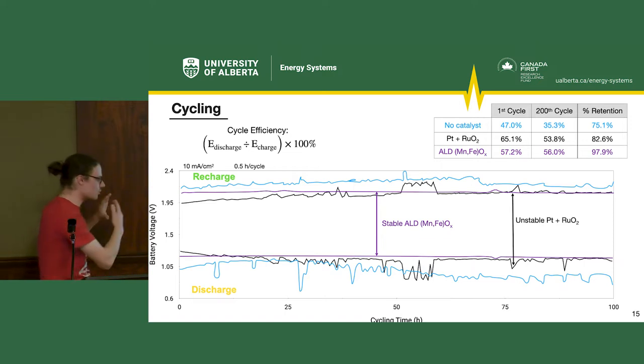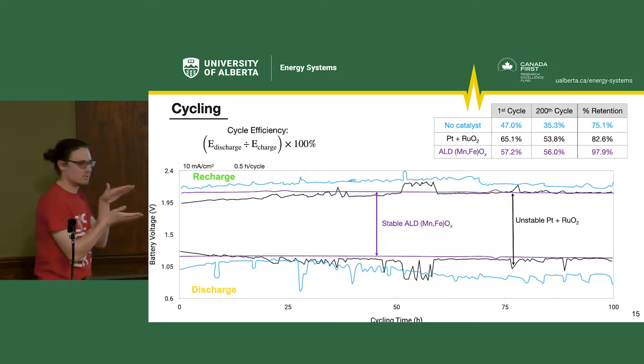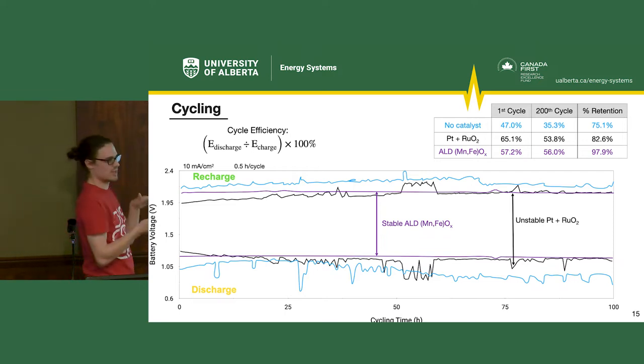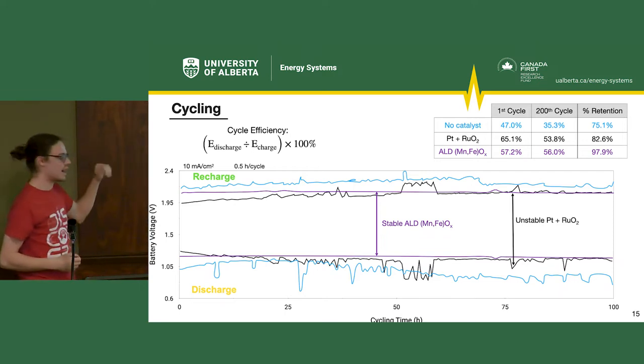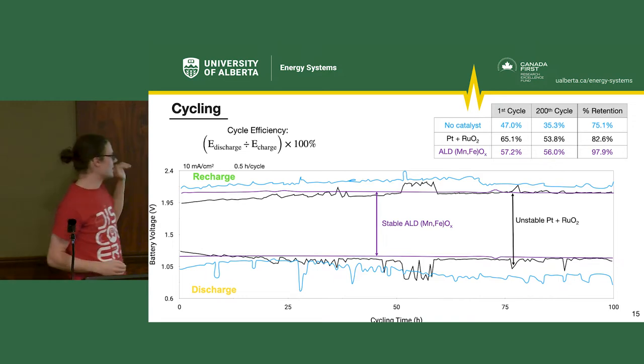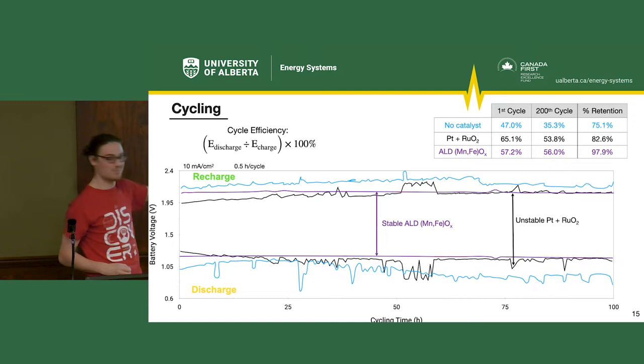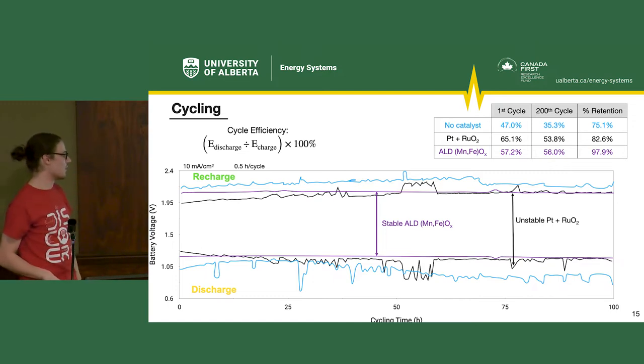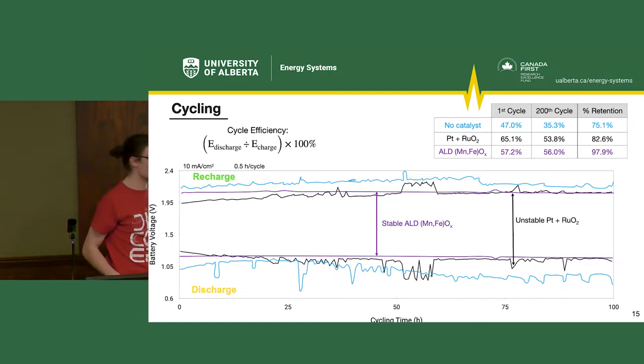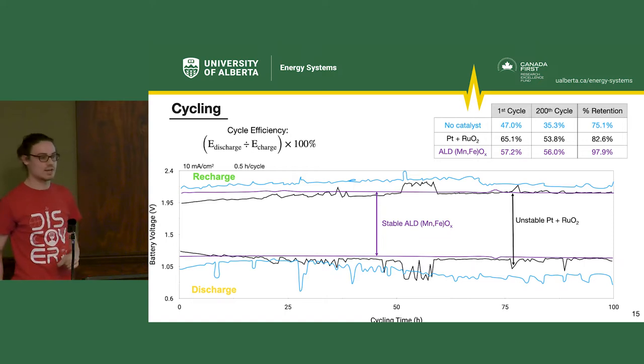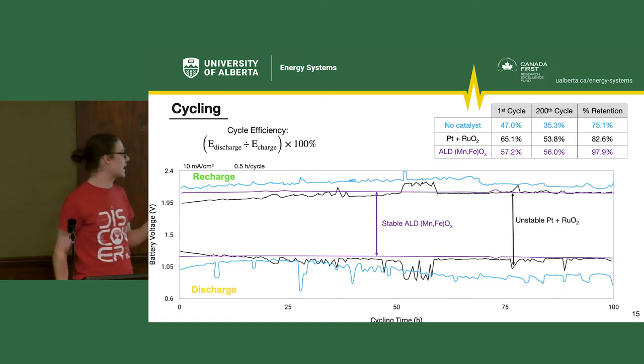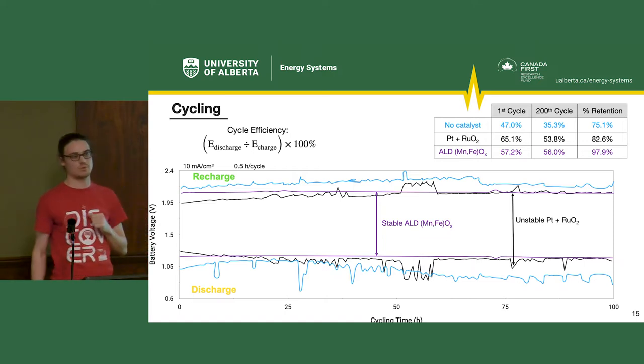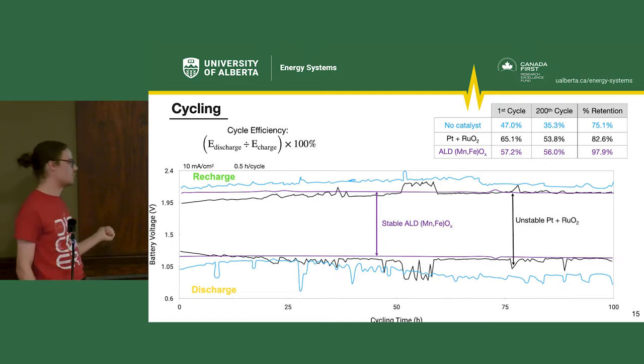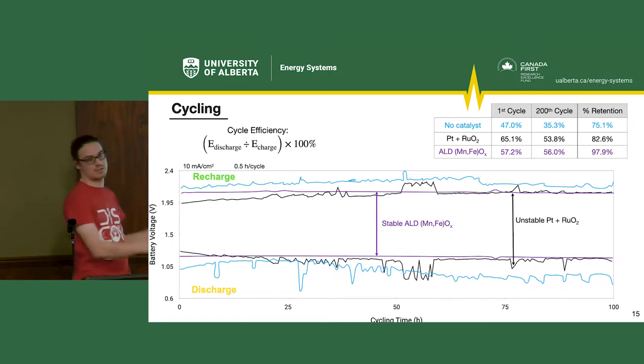But as I go through more and more cycles, that platinum starts to deviate away. It starts to get worse and worse efficiency values. My manganese oxide, my mixed manganese iron oxide, rather, is completely stable. That's a straight line pretty well. So at the very end, after 100 hours, the efficiency values for my manganese iron oxide is actually higher than the platinum and ruthenium oxide. So now it's actually a better battery after 100 hours of cycling.